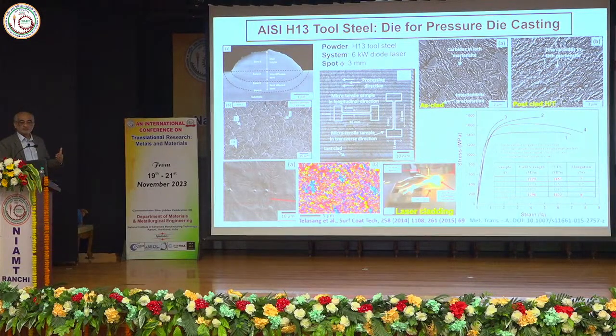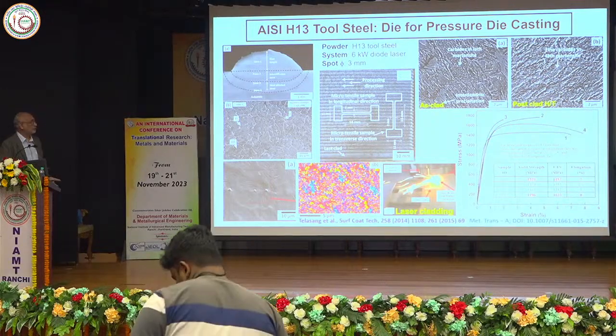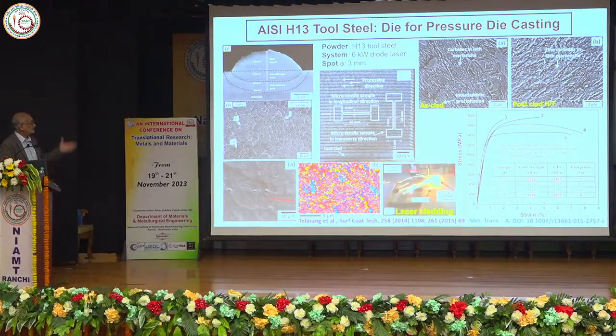Normally in H13 rolls or buckets, you would use a stellite coating, a cobalt tungsten carbide combination. So obviously two different compositions, the interface is a suspect, and most importantly the temperatures are different, and as a result when you refurbish, the repaired component also doesn't last too long. So he was one of the first to show H13 on H13, that's the first novelty. The second novelty is, if you look at these stress-strain diagrams, number 3 fails early, but numbers 4 and 2, which are from the H13 clad on H13 roll, show higher tensile strength, higher yield strength, and even greater ductility range.